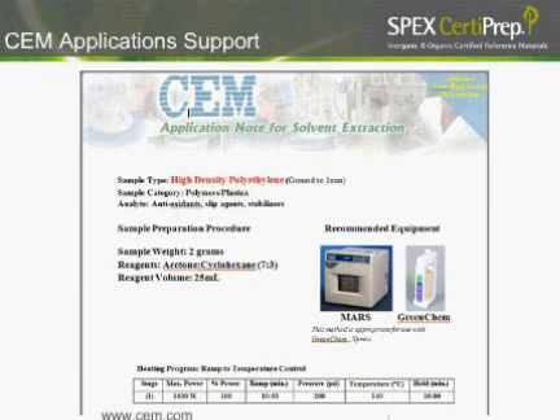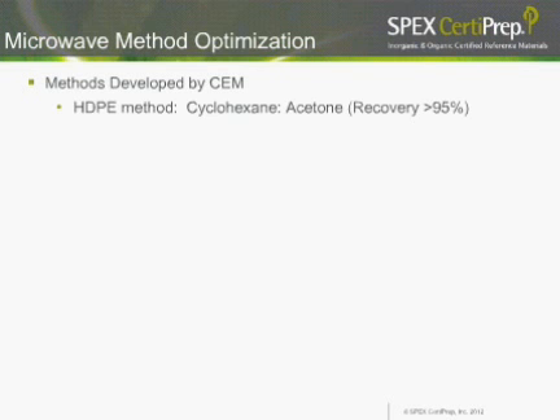Thank you very much. That's a good starting point from where we went with our microwave method optimization. We actually did look first at the methods developed by CEM, and I did speak to their application specialists at CEM to just verify some of the tasks we wanted to do to extract these polymers. And we did end up using the HDPE, or the high-density polyethylene method, as it was written, using the cyclohexane and acetone. We found a very high recovery, about 95%, when we used our CRM and that particular method.